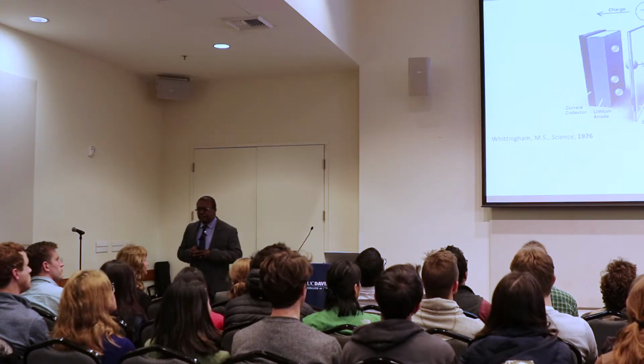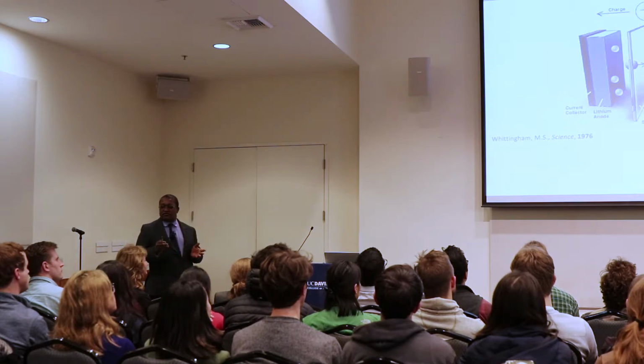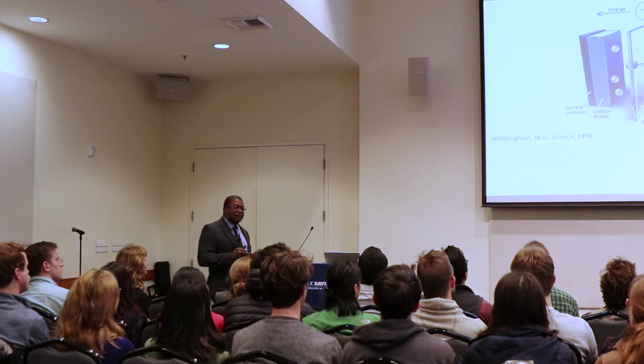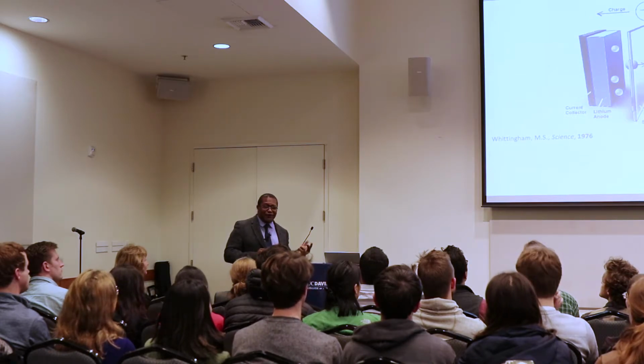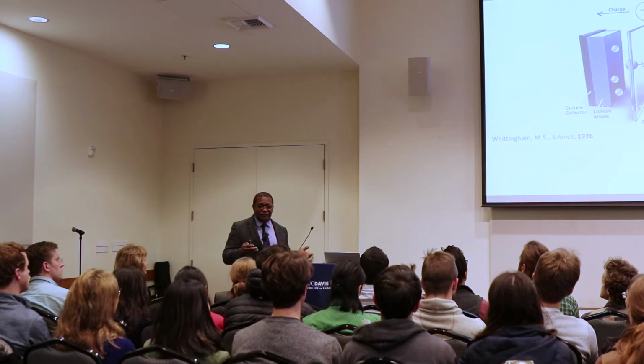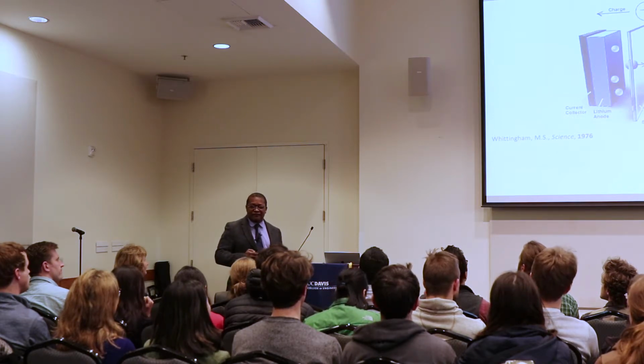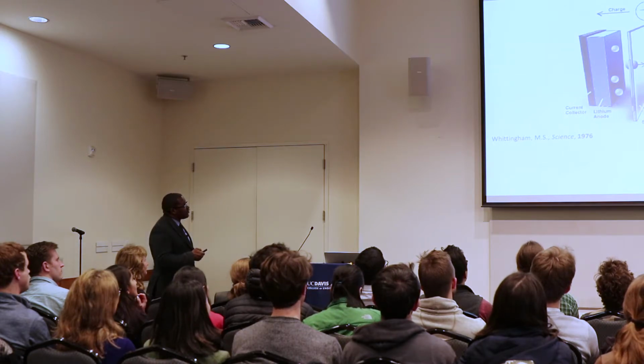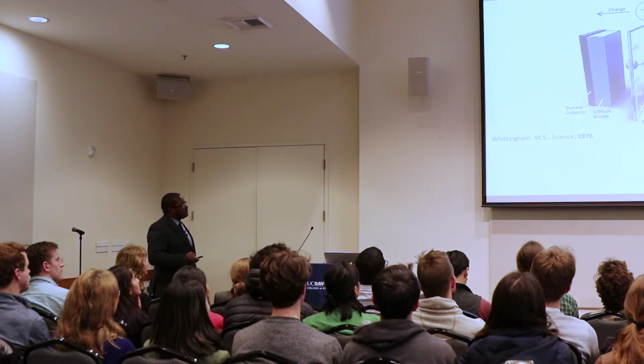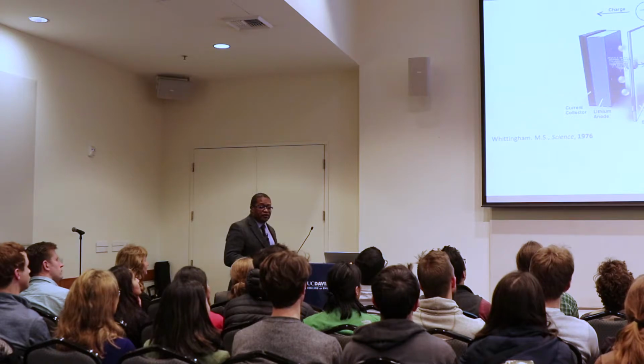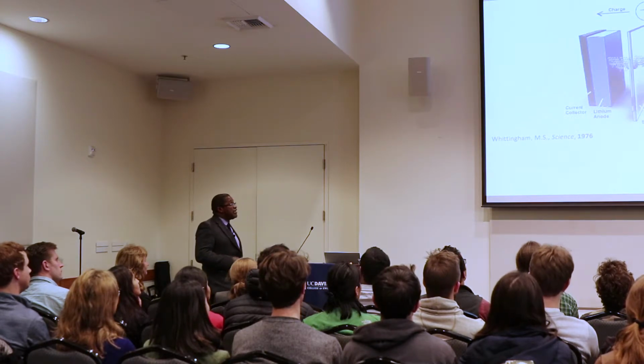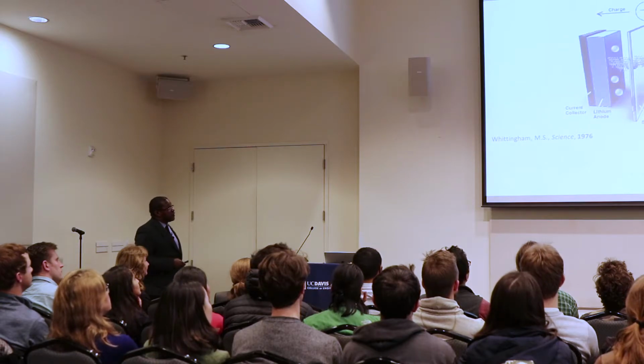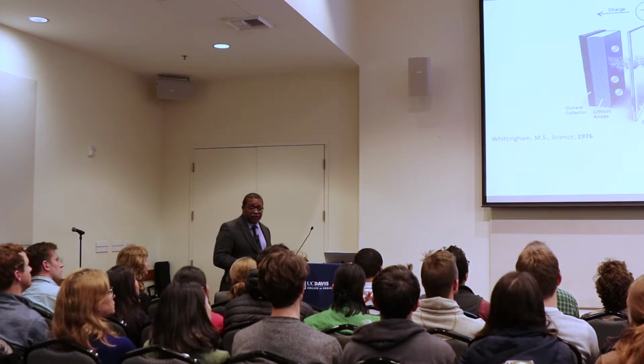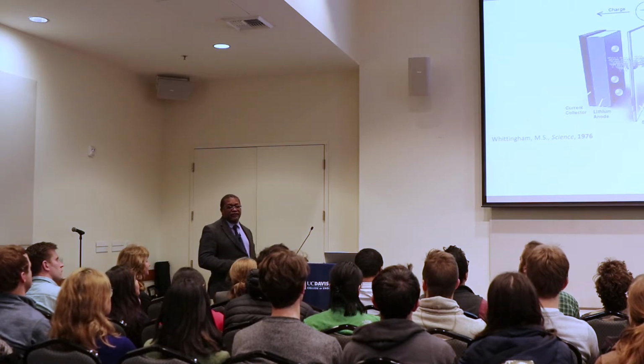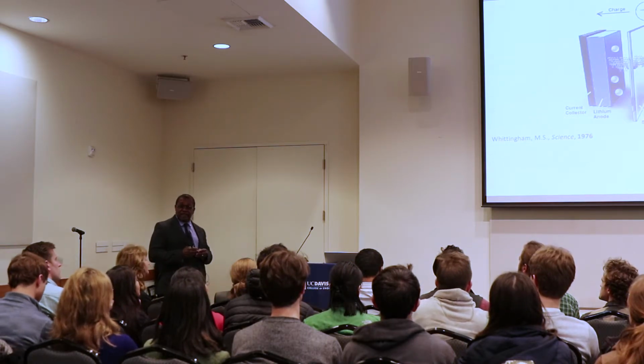So why is it a challenge? It turns out this is sort of like Back to the Future, because the very first lithium-ion batteries were, in fact, of the design I just described. They were because people knew intuitively that if you use a metal, it's simpler and costs less. But what they discovered is that when you cycle these batteries, charge and discharge, these are the lithium ions moving and depositing, you begin to grow structures on the lithium anode called dendrites. These metal structures very easily penetrate the polymer separator, cross over to the cathode, and short the battery internally. The ohmic heat generated as a result of that electrical short in a volatile electrolyte can actually cause a fire or explosion.